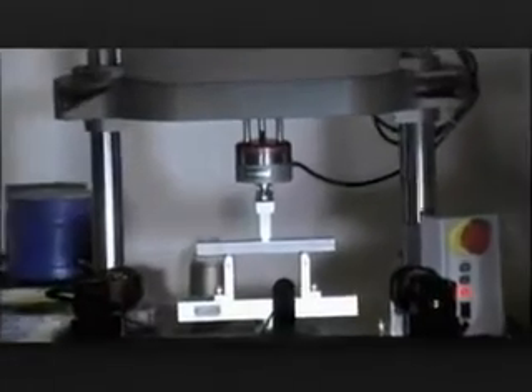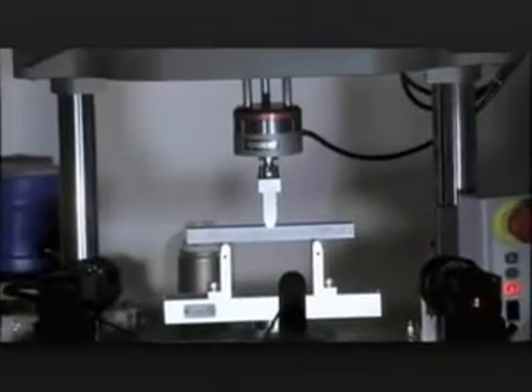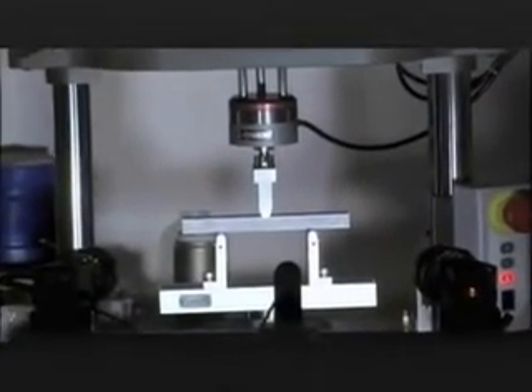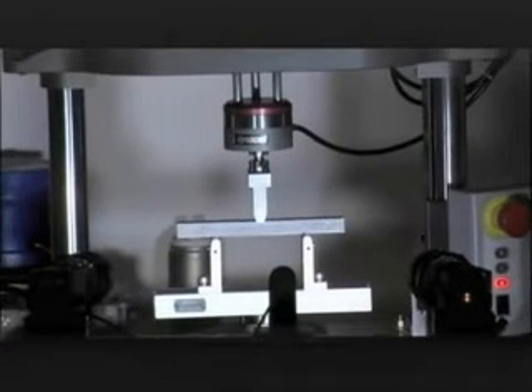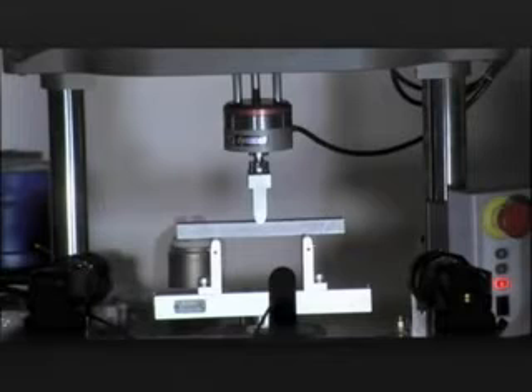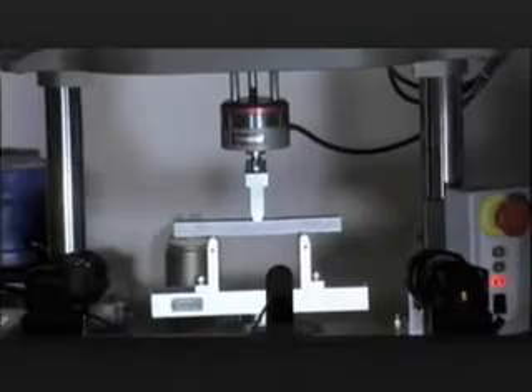So we're going to start to load up. I'll move out of the field of view here. So all being well, what we should see there is it's starting to deflect. Is it deflecting? Is anything happening there, Harry? Okay. So we're loading the sample up. There'll be a bit of indentation. And if you can, I know it's small, but if you look at what you're looking at there on the screen next to the Instron is in fact the load displacement trace.